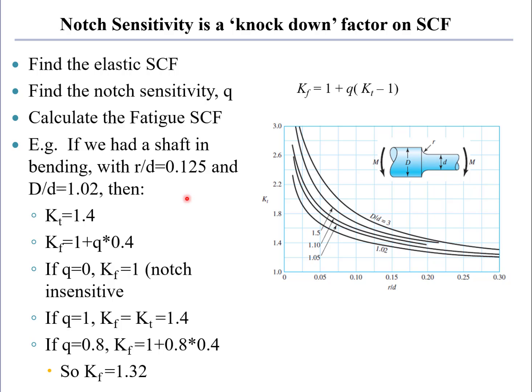So let's just imagine that we had a shaft with a fillet radius to small diameter ratio of 0.125, which would put us right in here. Imagine also that the D over d ratio is 1.02. So we're right here, which gives us an elastic stress concentration factor of 1.4. I show it here. The fatigue stress concentration factor, that's this equation right here: subtract 1 from the elastic stress concentration factor, multiply that by the notch sensitivity, add 1 back to it, and that gives us our fatigue stress concentration factor. So if we have an elastic stress concentration factor of 1.4, we subtract the 1 from it, which gives us 0.4. We multiply that by the notch sensitivity, add 1 to it, and it gives us our fatigue